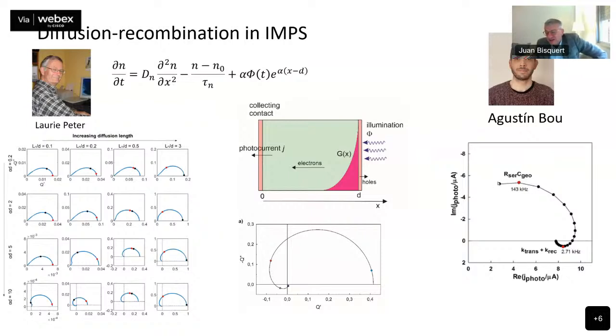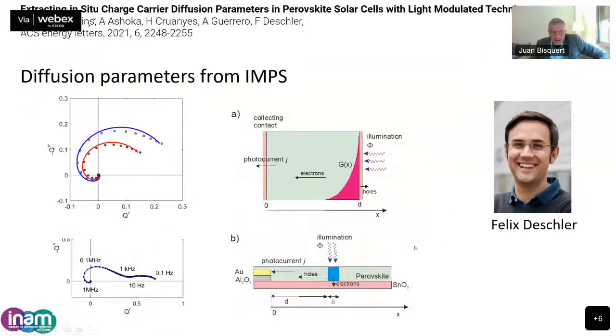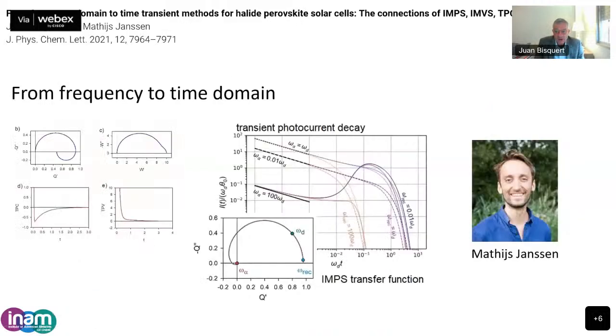But you see that it was sometimes suppressed, even by us, because you can see that this spectrum is going to be negative, but it has not been measured or it has been cut somehow, so it was not reported. So now we really could make this very reproducibly, and in combination with the group of Felix Deschler, we could use this part for fitting and calculate the electron transport coefficient, and it's a new method which is very successful. But also we can do the transients, etc.